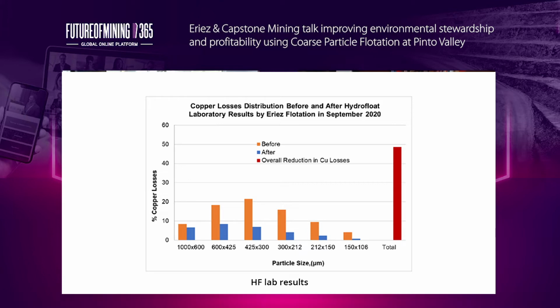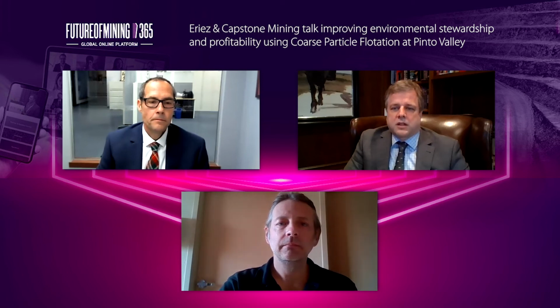Lab work done at Eriez showed that the HydroFloat could claw back a significant fraction of this in all size classes and reduce the amount of final tail in each size range, shown in blue. You can see that the HydroFloat gains are proportionally greater in size classes between 300 and 600 microns, where conventional flotation is very inefficient. The overall impact of the HydroFloat is to recover about half of the current losses, as shown by the red bar here.